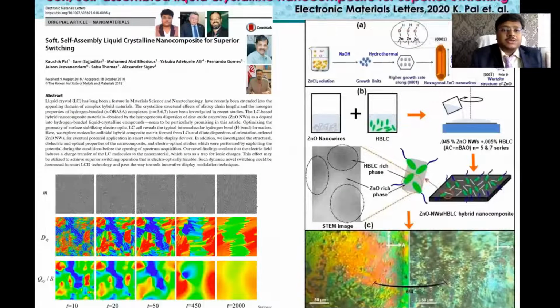And this is a soft self assembly of liquid crystal for superior switching application. This work is very interesting. We incorporated our theoretical ideas as well as experimental ideas. You can see here some electro-optical phase transition studies, and this is experimental studies in on and off states and simulated patterns of molecular orientation in different states of matter, solid, liquid, to isotropic, that we measured and that we calculated by simulation pattern theoretically.